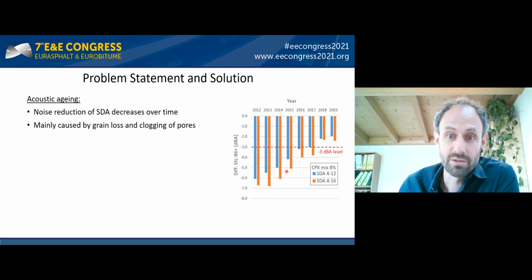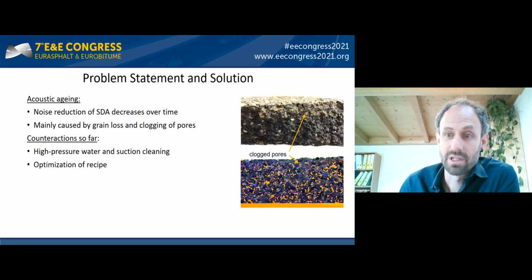During the first year, we gain from the higher void content with a better acoustic value. After, in the sixth year, both roads drop below the -3 margin. In the beginning, that acoustic aging is mainly due to clogging of pores. And in the SDA, this happens in the upper layer, which can readily be seen from cross-sectional images.